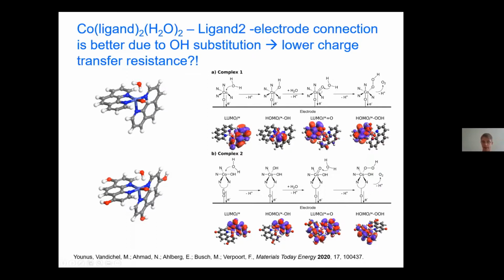that is very important to lower the charge transfer resistance. And we see that in each of the steps, so empty site, OH, oxo, and OOH, we have a conjugated system that allows electron transfer here from the LUMO back to the electrode. So that actually can explain why we have for complex 2 a higher current flowing as for complex 1, where the ligand should be oxidized during the catalysis. And if we then during the catalysis get some OH groups here, they can also anchor to the catalyst. But anchoring via this OH to the catalyst seems very sterically hindered if both ligands are still present.